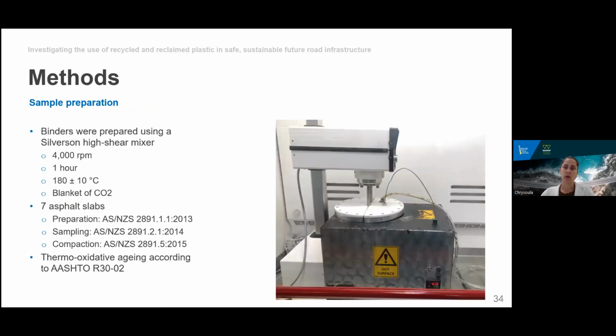To prepare the binders, we used a high shear mixer at 4,000 RPM. The binders were kept at 180 plus minus 10 degrees Celsius for 1 hour under a blanket of carbon dioxide, and that was to prevent oxidation. We then used these binders to prepare 4 slabs. Another slab was made using unmodified C170, and 2 more via the dry method incorporating the recycled plastics, as I mentioned earlier. For worst case scenario, we also subjected the prepared slabs to thermo-oxidative aging following AASHTO R30 method.